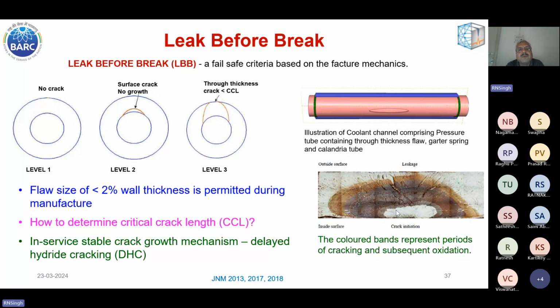There again, a CT sample is used, which is subjected to a load which will give a stress intensity factor more than the threshold stress intensity factor. We are more interested in knowing the DHC velocity of the plateau region, so the plateau region velocity is being used. So even though pictorially it is shown as a very shallow crack, for safety assessment we need to do the material testing under the most conservative condition.